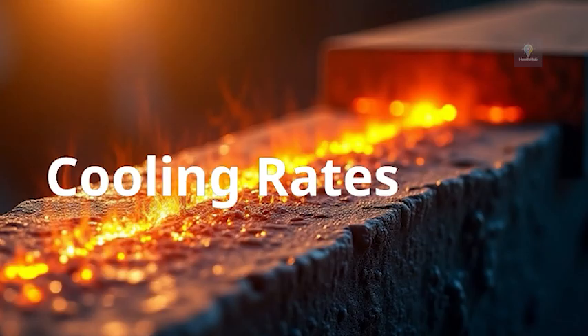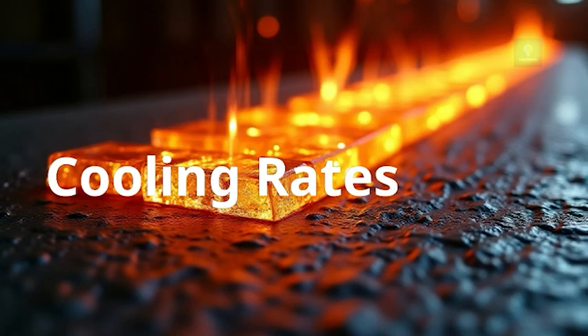This is similar to the TTT diagram, except each curve represents a different linear cooling rate. Cool a 1080 steel from 800 degrees Celsius at 200 degrees per second and you'll get martensite. At 50 degrees per second, you'll get a mixture of pearlite and martensite. And at 10 degrees per second, you'll get 100% pearlite.